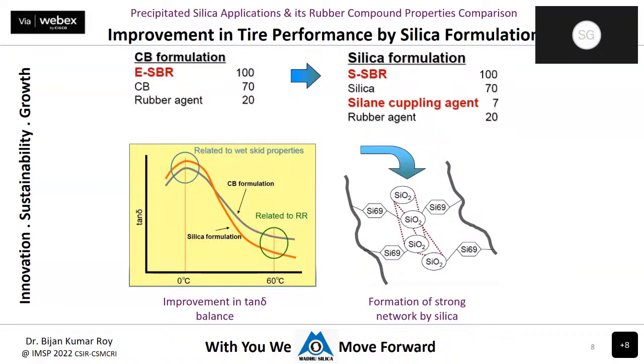If you compare with carbon black, the property is measured by a dynamic mechanical analyzer. So tan delta is a factor by which we can measure this. The tan delta at 60° centigrade is lower, and lower is better, that is low rolling resistance. And tan delta at 0° centigrade is higher for silica compound. So it gives better safety, that is the wet grip properties. So since there are two reinforcing fillers, carbon black and silica, when you're using a silica-based tire compound, it gives better rolling resistance. It gives higher safety, that is the wet grip properties, due to its inherent silica characteristics.